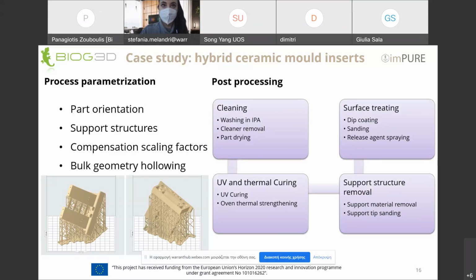qualities. Support structures must be removed with great care and the support tips on the part must also be sanded down in order to not leave any geometry defects. And also the surface must be treated using a dip coating technique, mechanical sanding, and some release agents must be applied in order to optimize the compatibility with the mold.